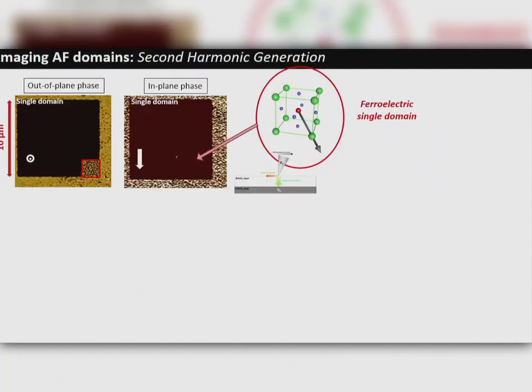And as a proof, I want to mention the pioneering work of Manfred Fiebig, where they managed to image, for example, some pure chromium oxide, where you can see, in the flop states, very nicely in a crystal the different antiferromagnetic domains. With some tricks, you can even see some 180 degree domains, so from here to here, which might be quite difficult, but you can even see it. And in this very nice paper, they image exactly our problem, because in this case, it's another multiferroic, the manganite, and they managed to decouple the image of the ferroelectric domains and the image of the antiferromagnetic domains.